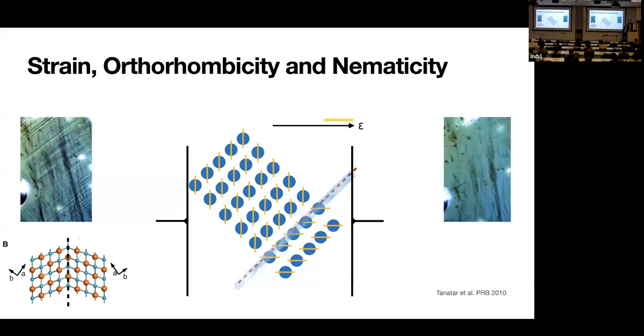And if you take that optical image again, as was done by Tanatar back in 2010, you can see that those little stripes, the domain walls, actually all disappear. So it shows you the generality of this idea. You have a broken symmetry. You know what that broken symmetry is. You choose a symmetry breaking field so you can control everything about how that symmetry is broken in your system, what fraction of it is in one direction or another, and that kind of gives you a control parameter over lots of different materials. And it also gives you, if you're trying to find out what that broken symmetry is, a probe of it as well.